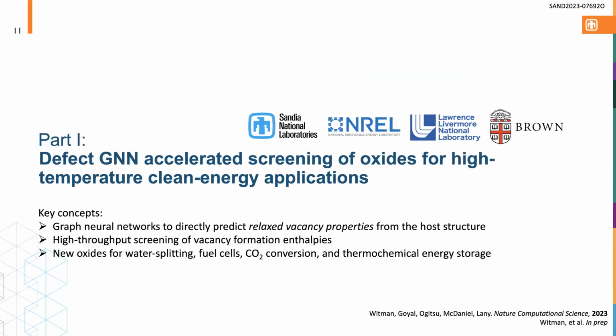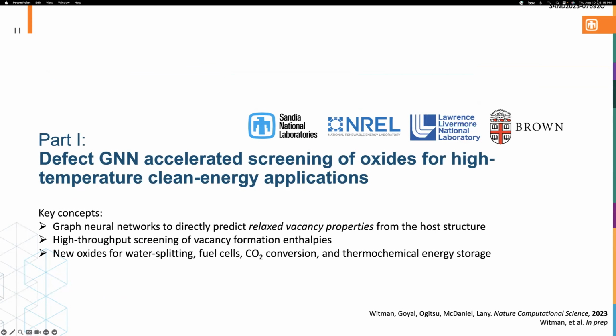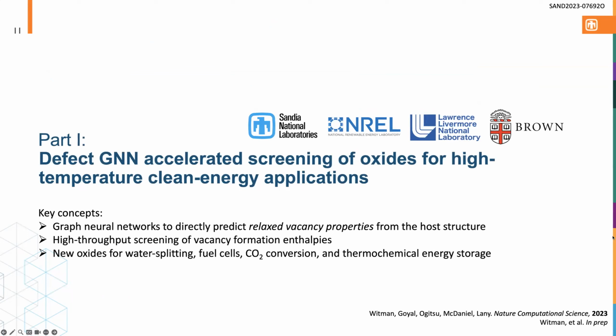So again, we're looking at what I'm going to call defect graph neural networks to accelerate the screening of these oxides. It's a national lab collaboration, including some work from people at Brown. The key concept is that we're going to use graph neural networks to directly predict relaxed vacancy properties from a host crystal structure. If you can do that, you can high-throughput new materials to predict this quantity and ultimately try and identify new materials that can do water splitting, operate as fuel cell cathodes, do CO2 conversion, and even thermochemical energy storage.